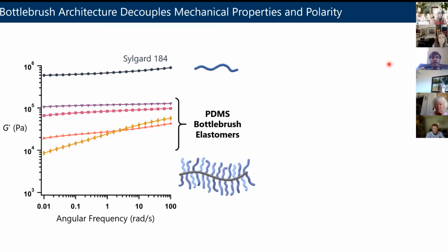Now, to put this into context relative to your standard materials like Sylgard 184 or rubber in your tire, what we're going to do is just plot that storage modulus, or the elastic contribution, versus the frequency. Remember, we said that we rotate the top plate back and forth, and so we can change the frequency of that rotation. When you plot it like this, if you've got a nice solid, you pretty much should see a horizontal flat line.